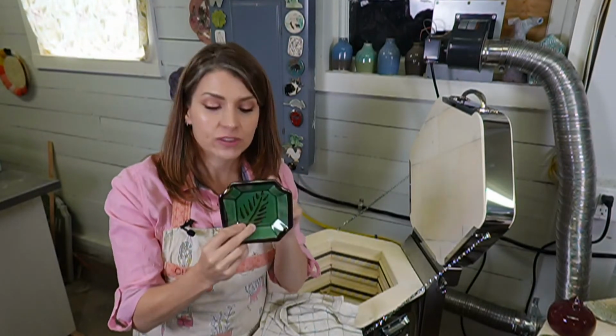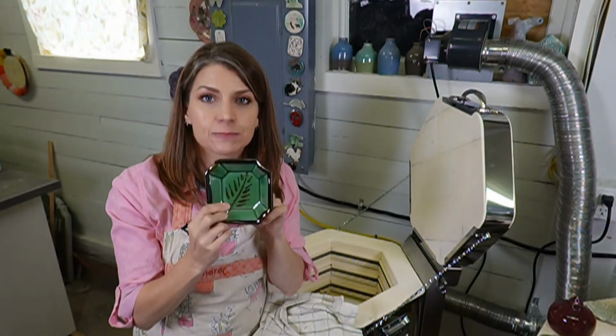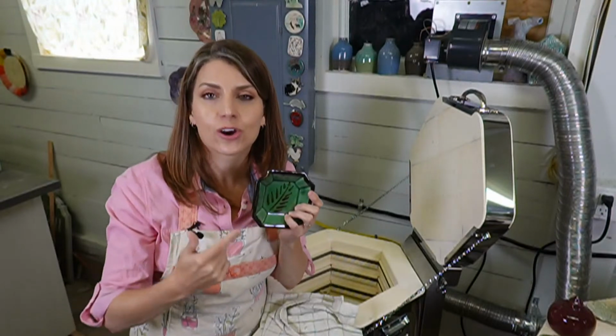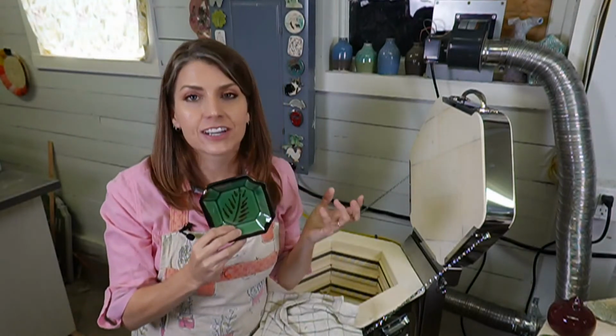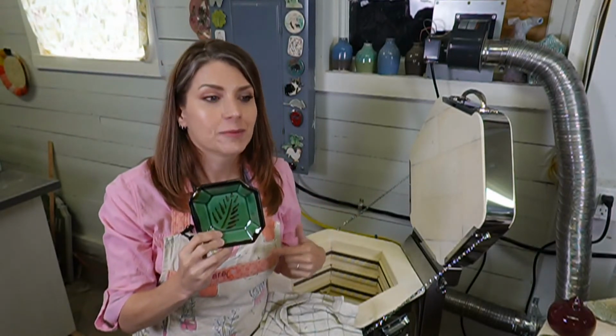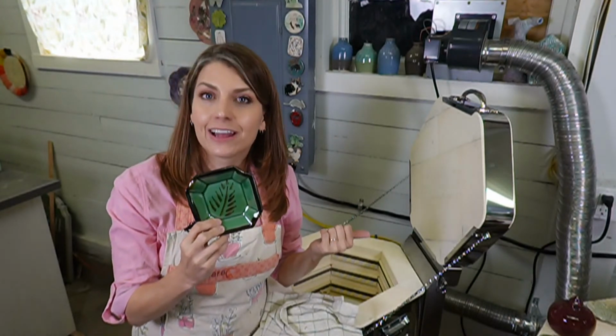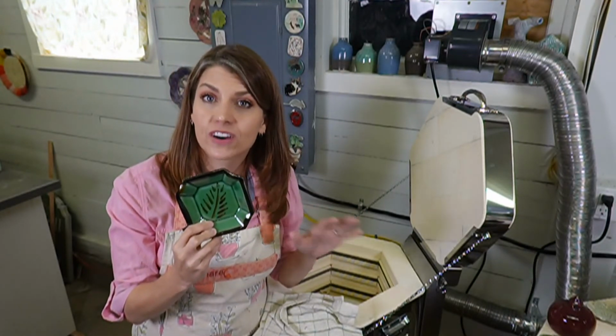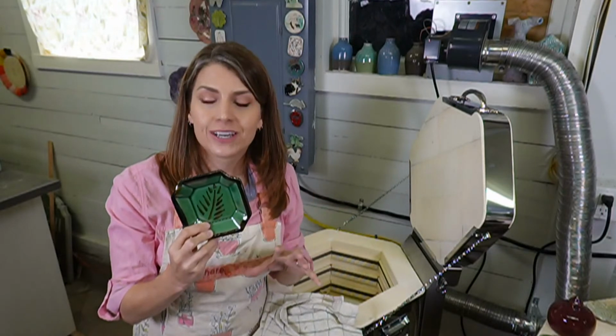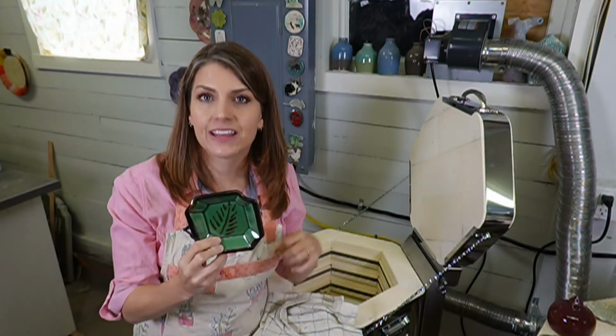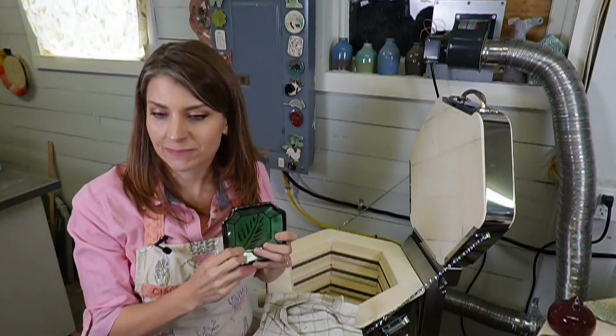But yes, so these are cone 5 glazes, but they can go to cone 6. This one can even go to cone 7 if it has to. And I have done it at 4, not intentionally, but in my older kiln, I had an element issue and it only got to 4 and it was fine. But you want to go to whatever temperature your clay says. You want to vitrify your clay, and that will be on the box from the manufacturer.